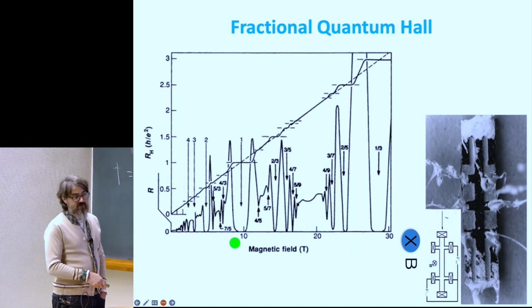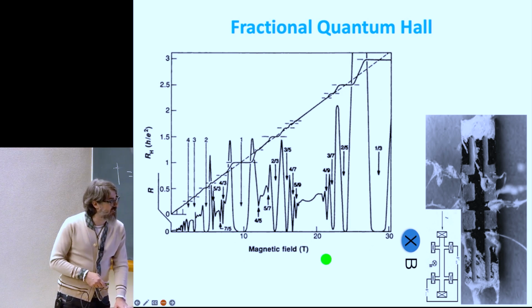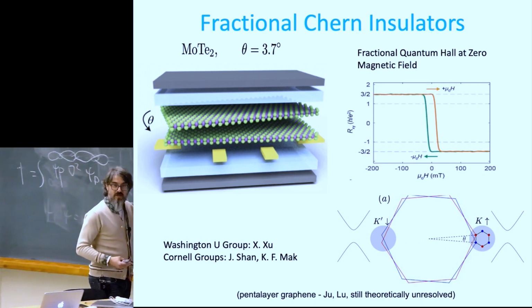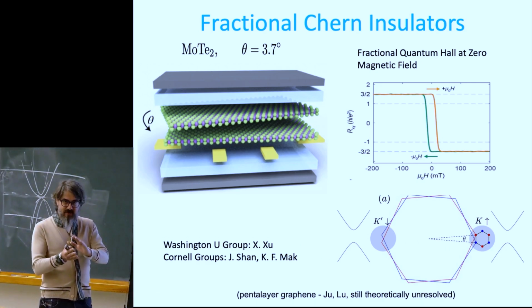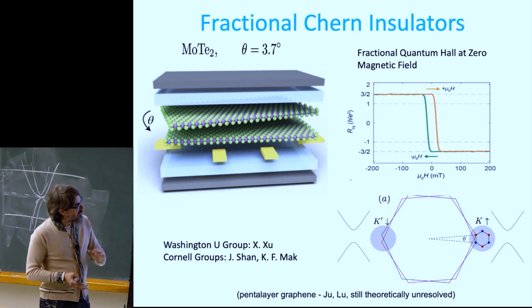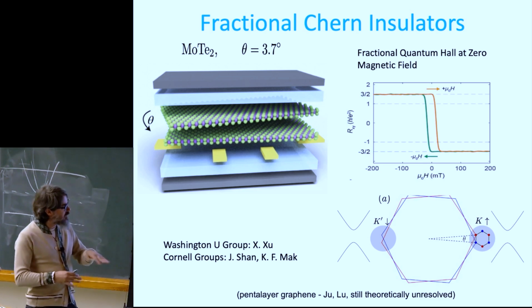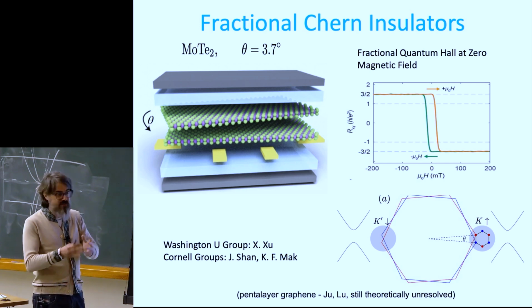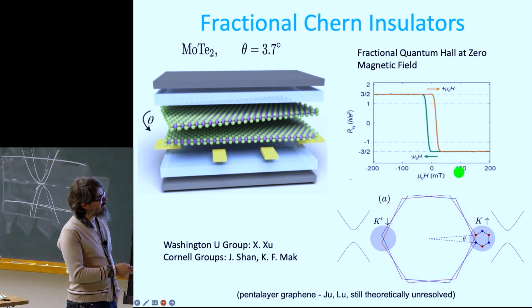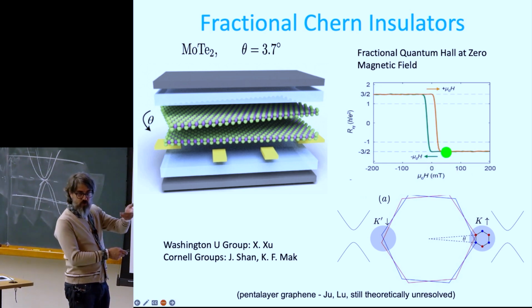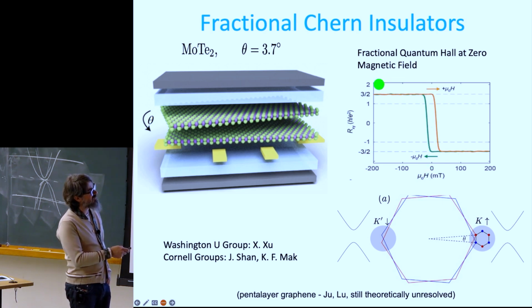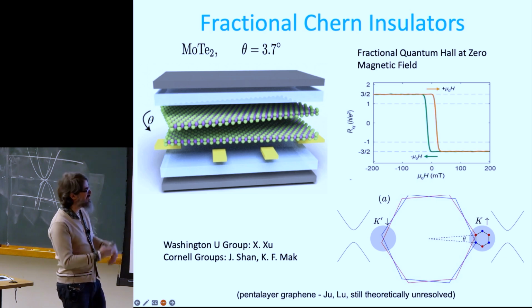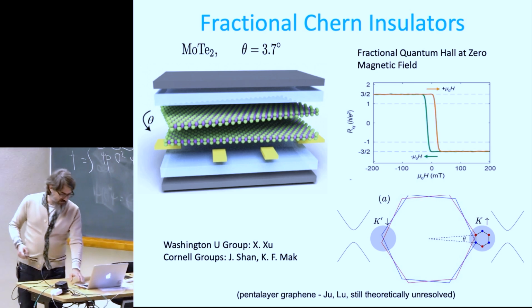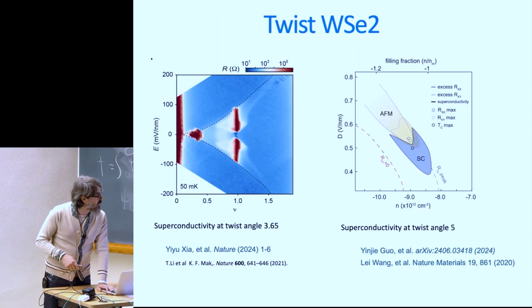So you can clearly see the magnetic field that's needed for these experiments. So now you can ask, can I have this state at zero field? And in fact, it's been done. This also is due to twisting. Due to twisting, you can get bands that are flat, so interactions are important. So just like Landau levels are flat, but unlike in stoichiometric samples, you can put a gate and control the doping and fractionally fill these flat Moire bands. And what you get, you can see the Hall resistance here at zero field. They put some field, which is very small, to orient domain walls, but at zero field, you can see you get Hall resistance of 3/2, i.e. Hall conductance of 2/3. This is the 2/3 Laughlin state here, which is just a material, no magnetic field. Okay, so there's other things such as superconductivity in twisted WSe2, which I won't go through, but this is hopefully some quantum simulator for Luttinger-Kohn.